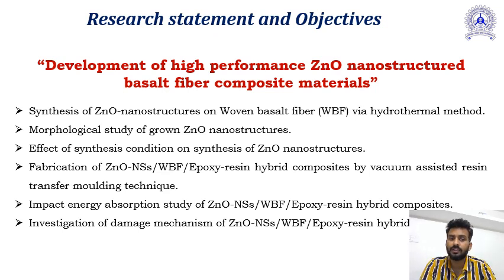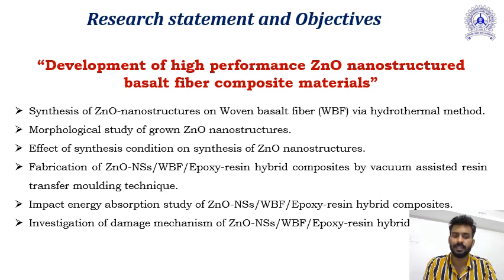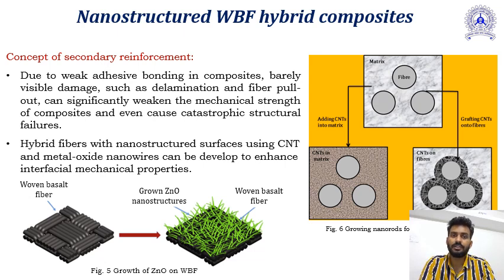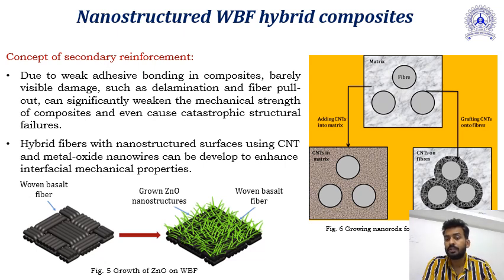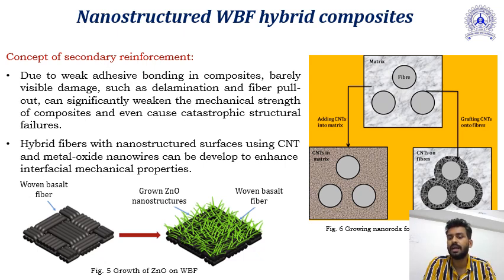We have synthesized ZnO nanostructure on woven basalt fiber via hydrothermal method, conducted morphological studies of the grown ZnO nanostructure, studied the effect of synthesis conditions on ZnO nanostructure, and fabricated the composite to study impact strength and damage mechanism. Initially, CNT was added directly into the matrix, which caused problems of agglomeration and dispersion. In this concept, we are directly growing the nanostructure onto the surface of the fiber using the hydrothermal method, which enhances the interfacial strength of the basalt fiber reinforced composite.